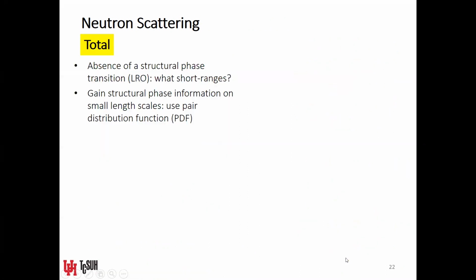So the absence of the structural phase transition made us wonder whether there might be something going on on the short scale. We didn't observe any structural phase transition with neutrons, nor with X-rays either. So the long-range ordering that occurs with a global change of crystal symmetry is absent in these materials. But we wondered if there might still be some type of changes in crystal symmetry on a small scale.